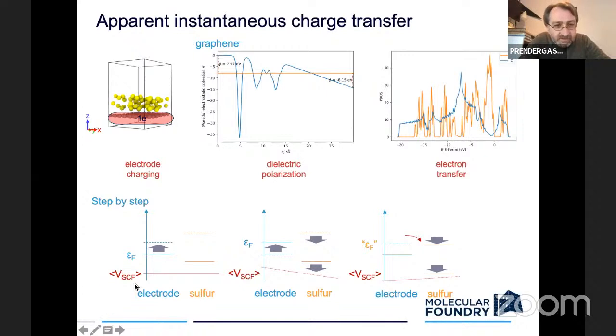underlying metal will start to offset as it follows this local potential. So in terms of energy levels, if I think of the electrode having its Fermi level here, and I want to raise the population of electrons by adding more electrons in the system, raising the Fermi level, then the position of, for want of better terms, the band edges or the HOMO and the LUMO of the sulfur molecules, they will start to shift downwards as this average self-consistent field or local potential responds to the presence of the excess charge on the electrode. Okay, so it's just simple electrostatics. But at some point, if the charge on the electrode is sufficiently large, the LUMO of this molecule will dip below the Fermi level and spontaneously accept that electron. And now the self-consistent field will rebalance itself because now you have a different direction of your charge.